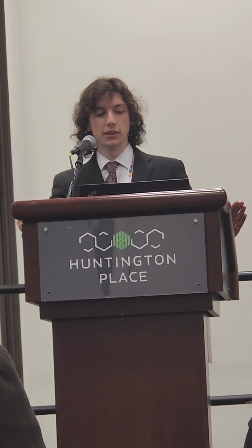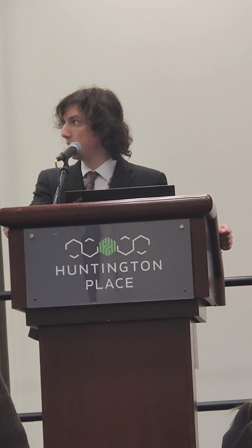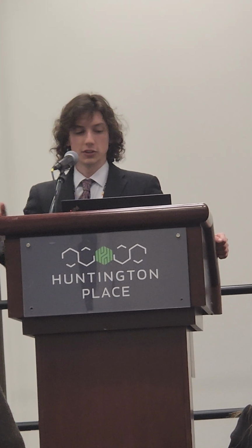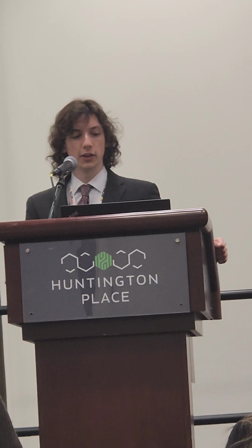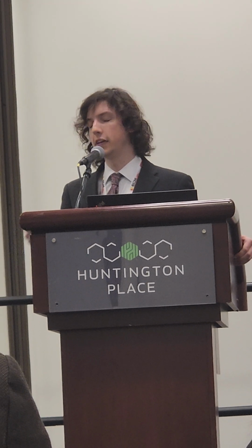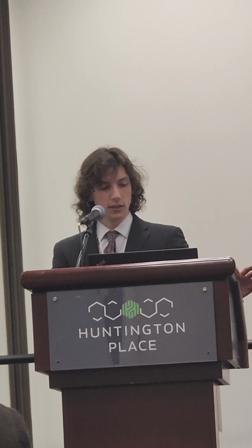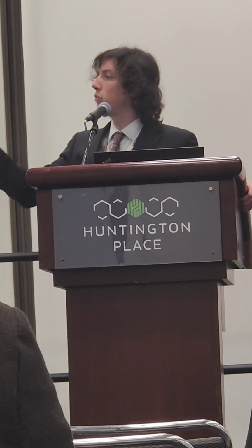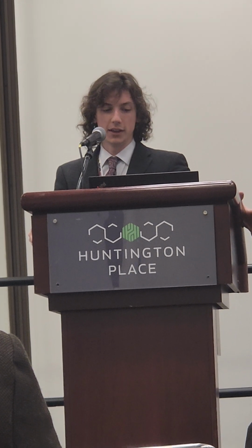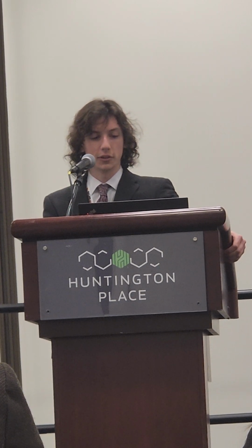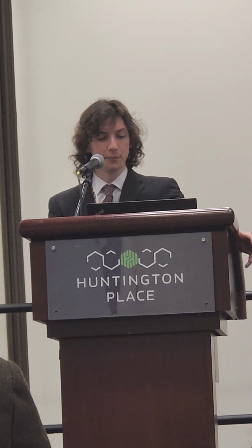So for how the prior austenite grain size is measured, I used a MATLAB function to expedite the line intercept methodology. The niobium modified alloy I'll refer to as 4121 niobium, and the standard alloy I'll refer to as 4121 aluminum, as you can see on this slide. And this is the niobium modified alloy after 328 minutes at 1664. The way I did it, I clicked wherever the lines intersected with grain boundaries, and that gave me the intercept lengths. So I got a distribution for all of the grains within the samples I looked at.